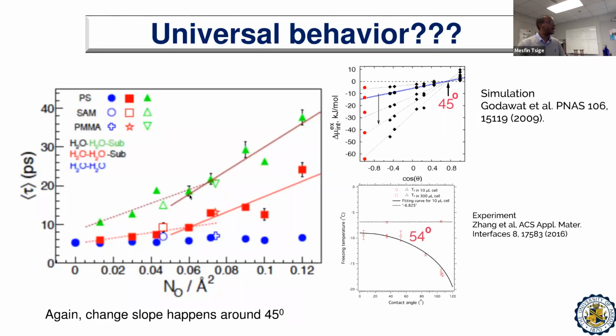In our case, looking at the hydrogen bonded network, what we have found is that at this degree of oxidation, the water molecules forming hydrogen bonds with the substrate show some kind of percolation. Pretty much that happens around this value. Once that's achieved, we don't see a change in the diffusion coefficient and a few other properties. So we correlate the hydrophobic to hydrophilic transition directly to the percolation of the hydrogen bonded network on the surface.